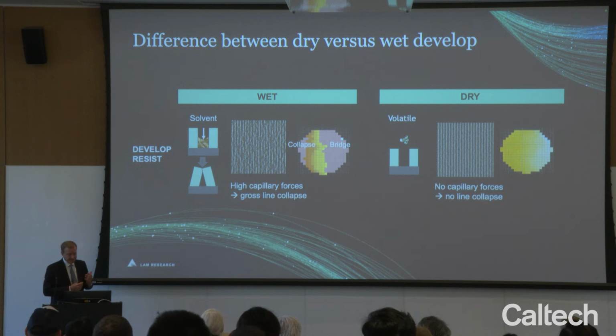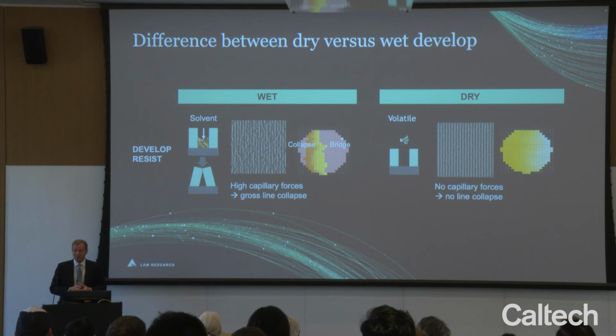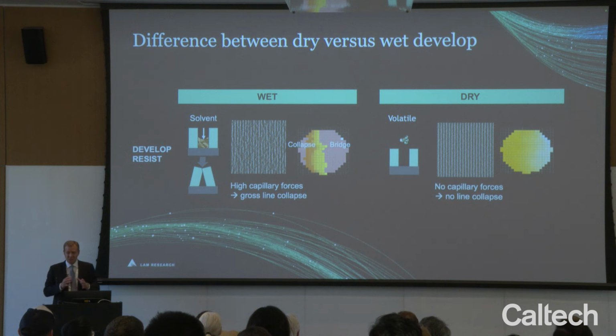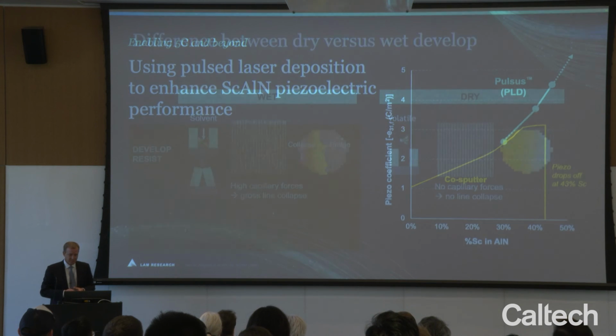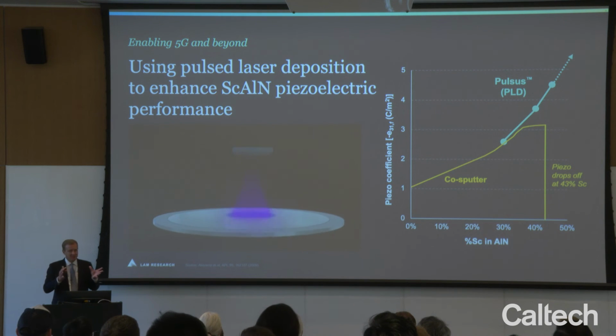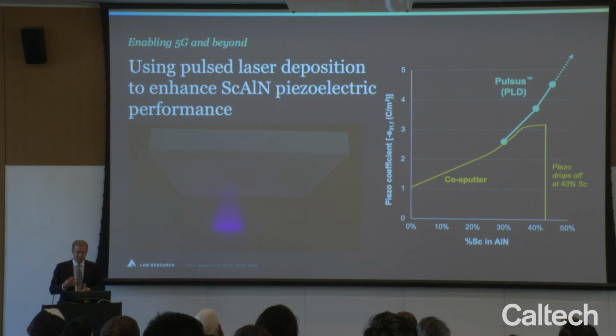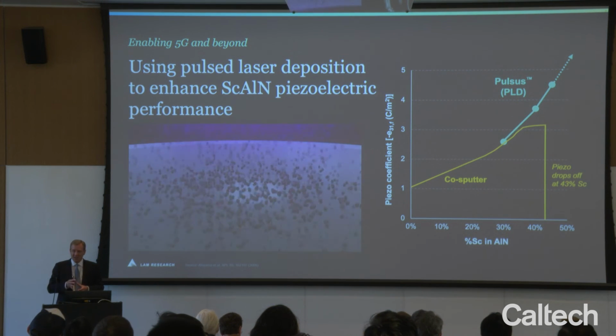And so you can see here, on the left side, the pattern obviously looks pretty messy. These patterns have collapsed on top of each other due to those capillary forces. And on the right side, you see a very nicely printed pattern as a result of using dry develop. So again, not really changing the fundamental objective of what we're trying to do, but really changing the method by which we're doing it allows us to achieve a better result.